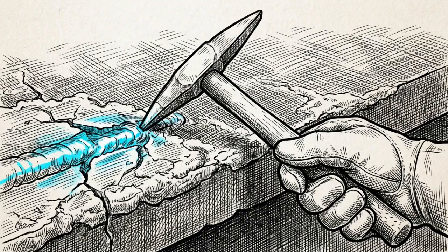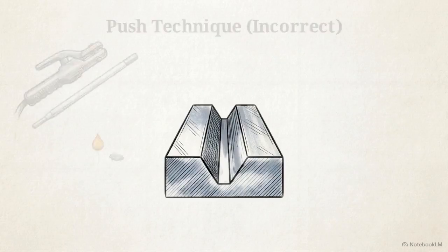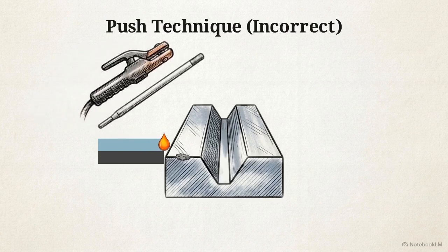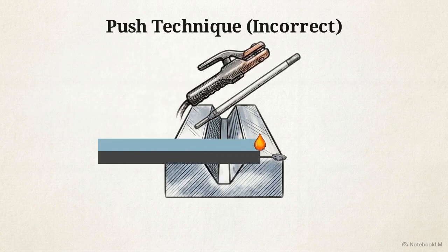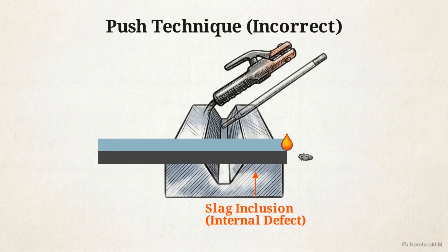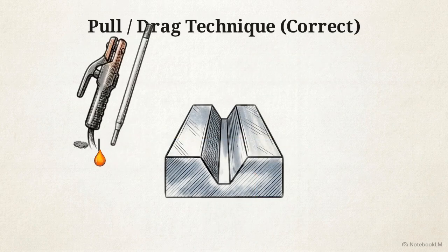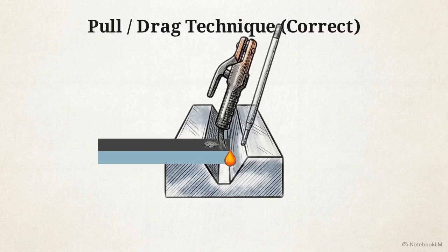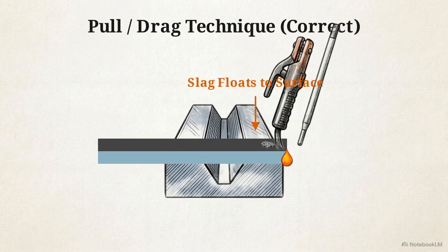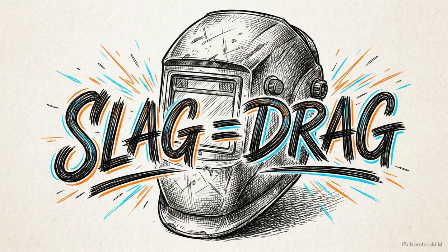It depends entirely on whether your welding process produces a layer of molten slag. Pushing stick or flux cord wire drives molten slag ahead, burying it under liquid weld metal. This creates a hidden slag inclusion that fails inspection. Dragging prevents this. Pulling backward lets the arc strike clean metal, allowing slag to safely float on top. This is a non-negotiable rule for beginners and code welders alike. If there's slag, you drag.